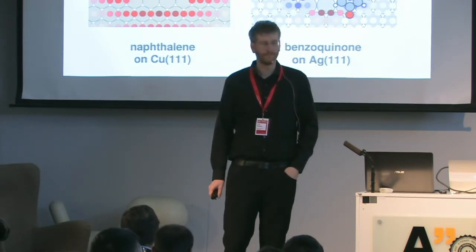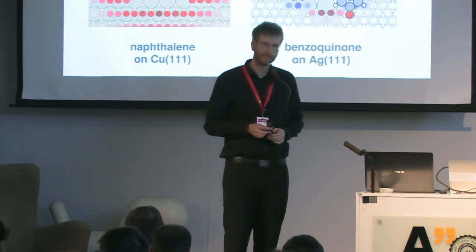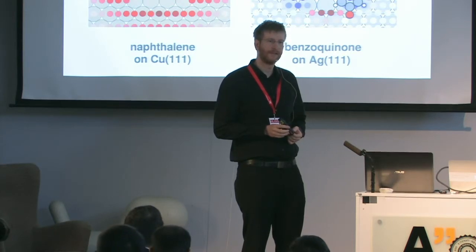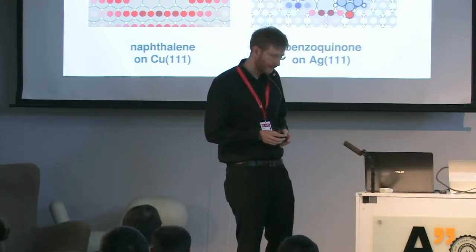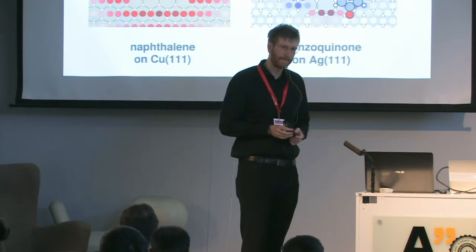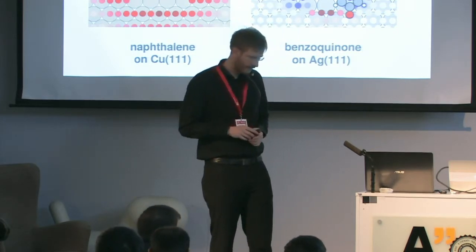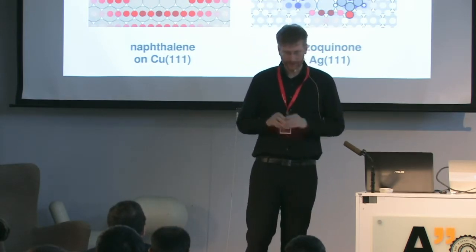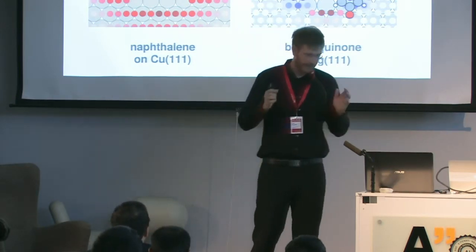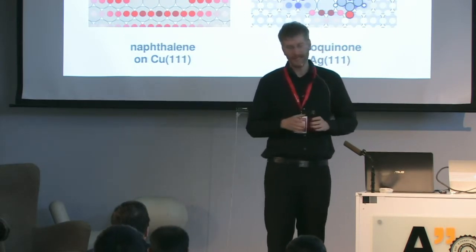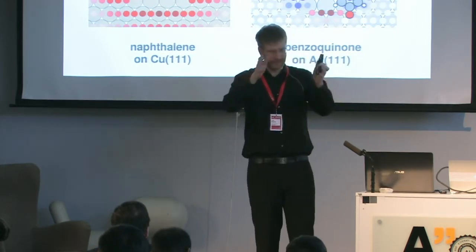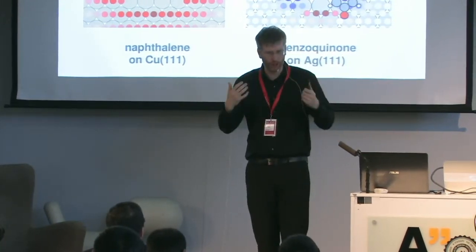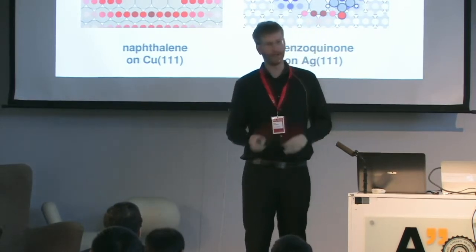Thank you for the talk. I was wondering, when you generate the training data, do you fix the molecules epitaxially at specific positions without relaxing them? Because my belief is that in a real simulation, if you put two molecules together, they might not be any more situated at the perfect HCP or top position. That's an excellent point. So this assumption of commensurability carries the implicit assumption that the potential energy surface of a single molecule on the surface, the potential well it sits in, is deep enough so that it doesn't get pushed out from that by molecule-molecule interactions.